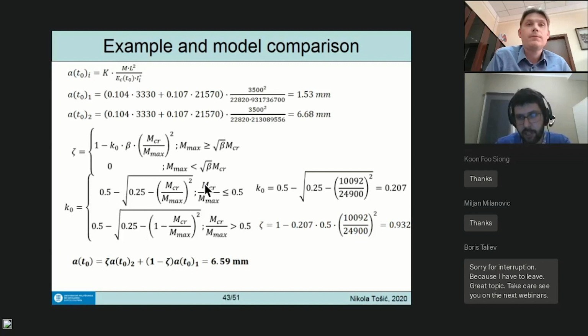K0 depends on whether the ratio of cracking to maximum moment is less or greater than 0.5. When it equals 0.5, the value will be 0.5. In this case, the ratio is 10/25, so we get K0 of 0.207, further decreasing our beta. Since we're calculating a long-term deflection, it still goes as 0.5, and we get a high zeta, 0.932. So we get an initial 6.59 millimeters.